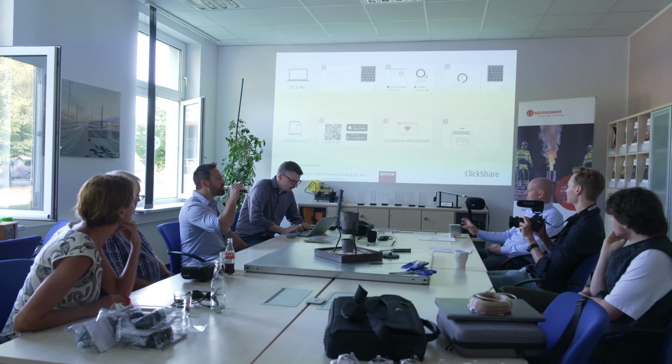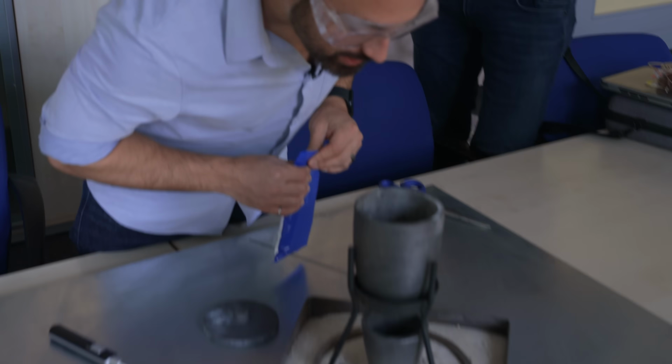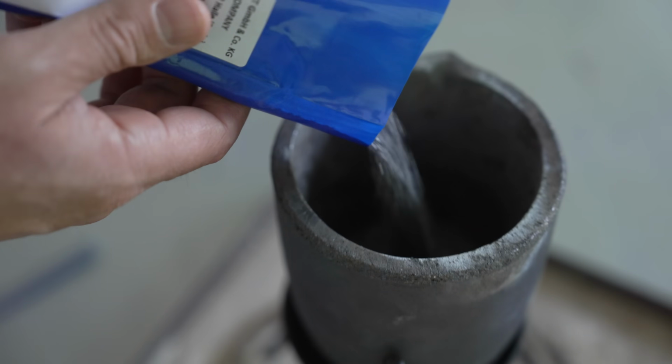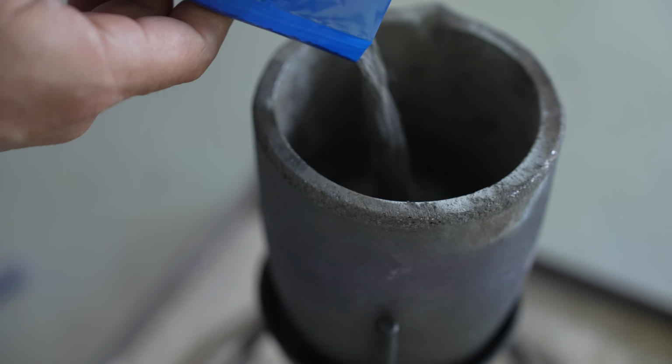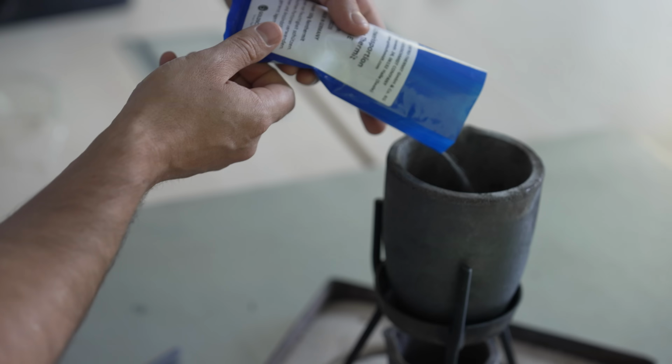They have the ingredients so dialed in that you can actually ignite thermite indoors without fear of molten metal flying all over the place. This mixture includes some pieces of pure steel. They don't participate in the reaction, but they do absorb heat as they melt, so they help control the rate of reaction and the temperature reached.